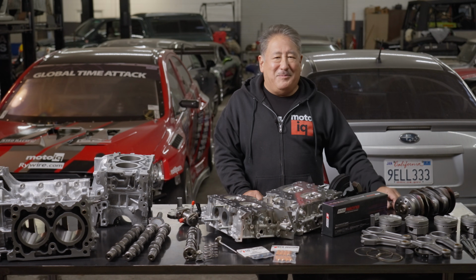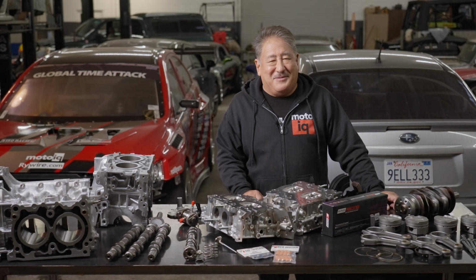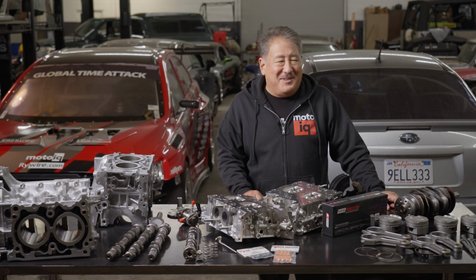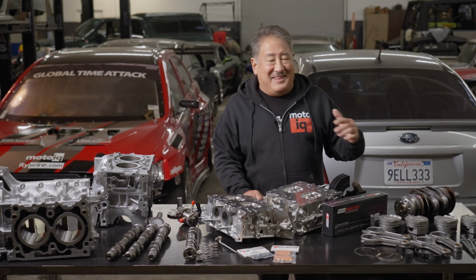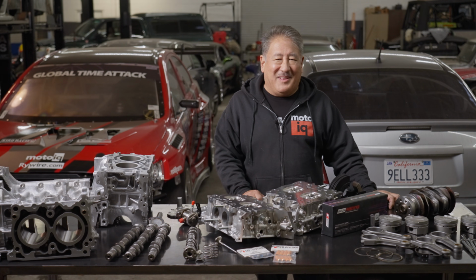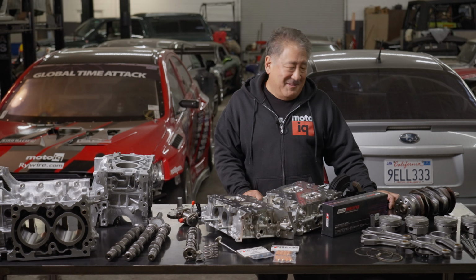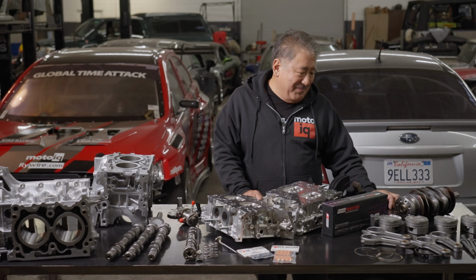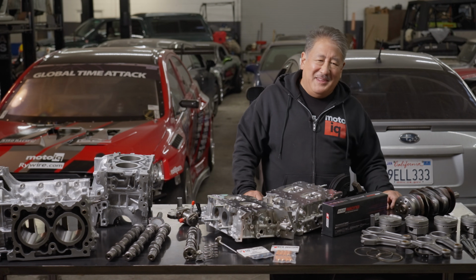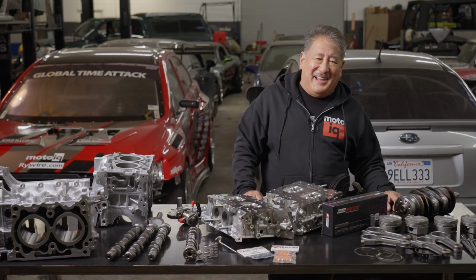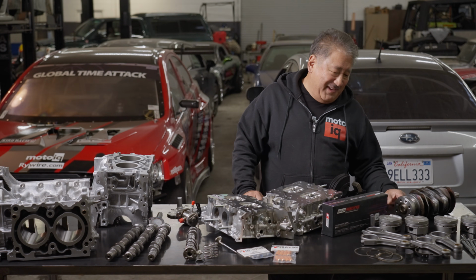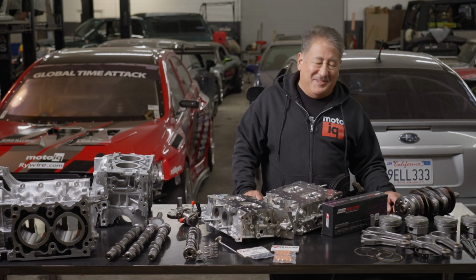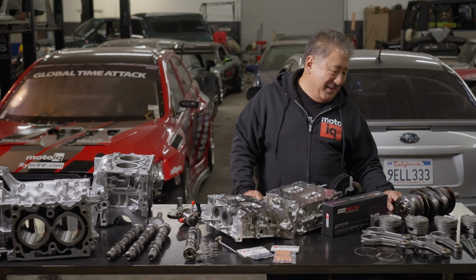WPC generally increases the fatigue strength of a part by about 100%. This isn't tensile strength, but more like the number of cycles before failure. So that's improved about 100%. WPC reduces the likelihood of cracking, helps fatigue strength, and reduces friction. So it's a winner all around.